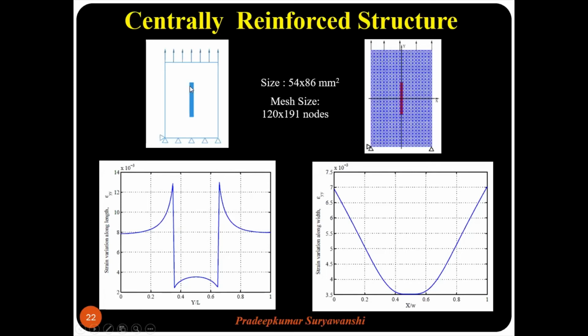It is expected that when a tensile load is applied, this inclusion or reinforcement will take up the complete load, and that will happen through the shear lag model, or the load transfer between the matrix and reinforcement at this interlaminar position. Okay. A similar model for the MSS model is shown here. We performed the simulations and plotted full field displacement, full field strain, full field stress, as well as the variation of epsilon yy, that is strain in y direction, along the length and along the width of this structure.